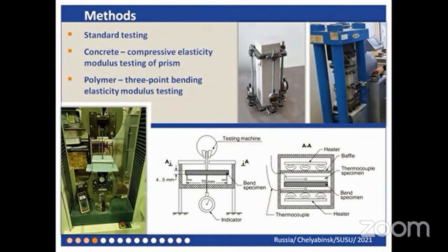In the research, different methods of elasticity modules testing were used for cement and polymer composites. Standard methods of Russian state standards were used for concrete modules of elasticity determination. The elasticity modulus has been determined as a relation of 30% cracking stress to the sum of elastic relative deformation, except plastic, on stages defined by the standard. For polymer samples, the bending test of elasticity modulus was used.